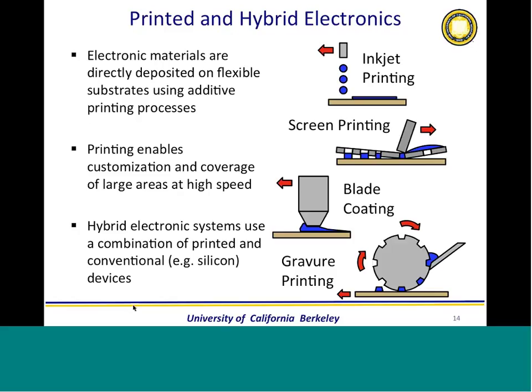With screen printing. And we also use a lot of blade coating because these materials, especially the semiconductors, are somewhat low viscosity solutions. Sometimes they are dissolved in organic solvents. And the technique is very simple, where you just wet a blade with the meniscus of your solution and you spread that solution over a substrate. It's really just like spreading butter on bread, but more exciting.